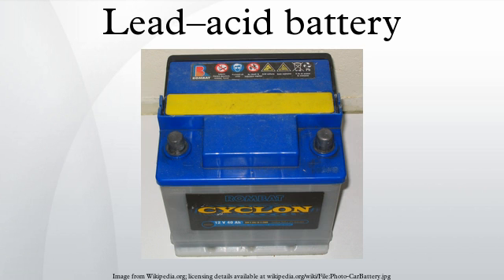To deal with these events, AGMs often include a one-way blow-off valve, and are often known as valve-regulated lead-acid, or VRLA, designs. Another advantage to the AGM design is that the electrolyte becomes the separator material, and mechanically strong. This allows the plate stack to be compressed together in the battery shell, slightly increasing energy density compared to liquid or gel versions. AGM batteries often show a characteristic bulging in their shells when built in common rectangular shapes.